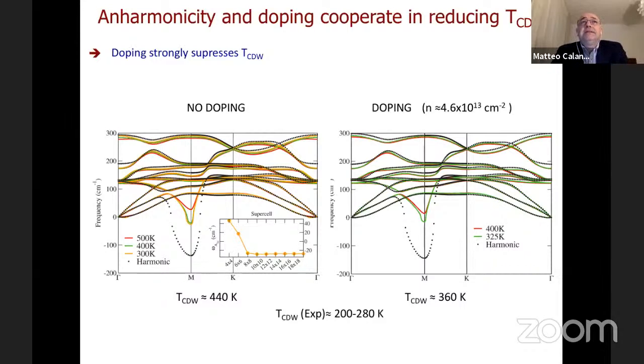So what happened is that we are looking at the charge density wave transition from the top. So we are looking at temperatures larger than the charge density wave transition, and we are looking at how the mode becomes soft. So in this case, above the charge density wave transition, omega squared goes linearly, so omega goes essentially as the square root of T minus Tc. However, below, this is not given. And indeed, what we find is that there is a different behavior below of the phonon, which is imaginary, because what should happen at this point is that you release the lattice, the lattice changes shape, and so the phonon frequency changes completely.